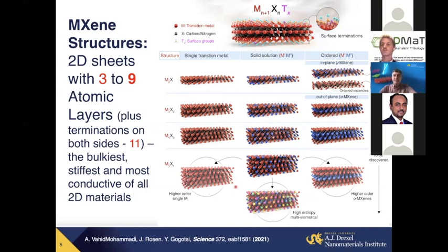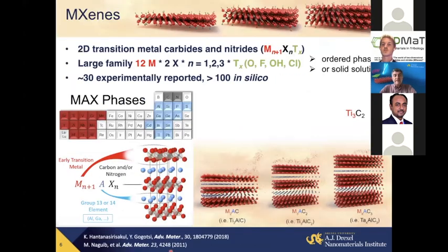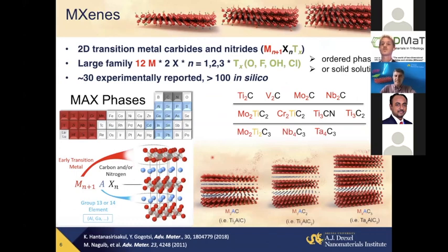So they really behave like straight sheets on the surfaces here, at least the thickest one here. Now, we can make them in many different ways. Typically, we use etching. We remove an element by etching in sulfuric acid, hydrofluoric acid, or hydrochloric acid solutions, and so on. And you can form a variety of structures because we need to remove a layer